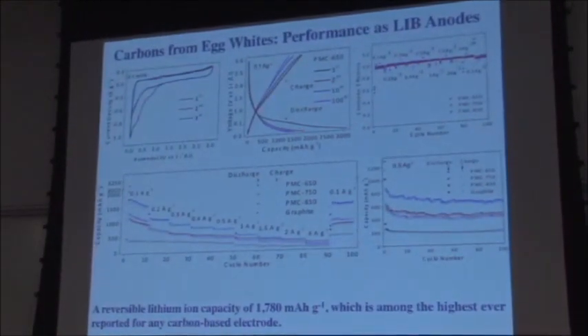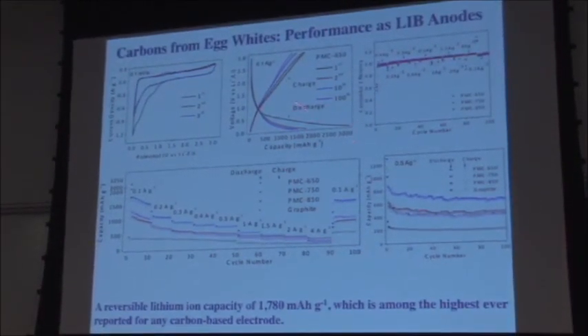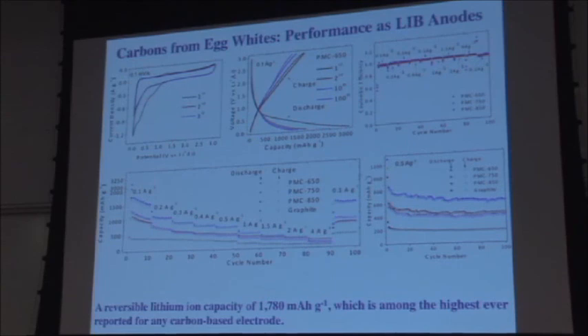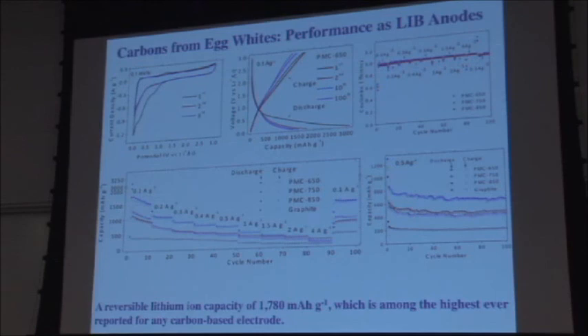So when we looked at lithium-ion battery performance, of course during cycle 1 we had fairly significant capacity loss, but after cycle 2, we got 1780 milliampere hours per gram capacity. That's your reversible capacity after cycle 1. It stayed fairly stable. You had a bit of a decrease, but basically you formed a lot of SEI layer. The first discharge capacity is not meaningful. The second one is. So these are the CV curves. Your voltage profiles look fairly similar to graphite. Your Coulombic efficiency is quite high after cycle 1, of course.